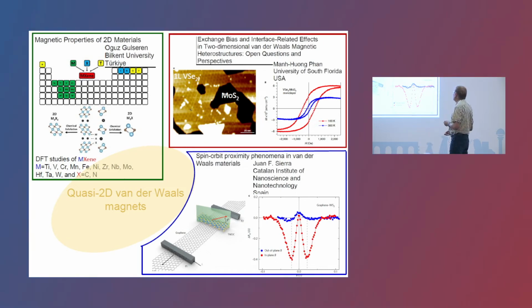On the other hand, the enhancement of the critical temperature of the van der Waals magnet was shown, for instance, a very spectacular enhancement of the critical Curie temperature of vanadium diselenide, which was put on a substrate of molybdenum sulfide. The critical temperature was raised up to room temperature, and a very nice hysteretic magnetization curve was shown, measured at 300 Kelvin.